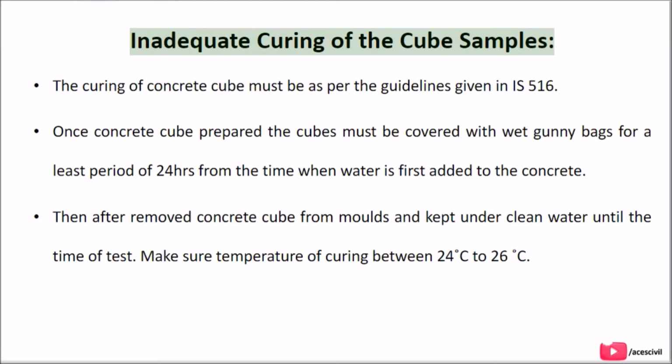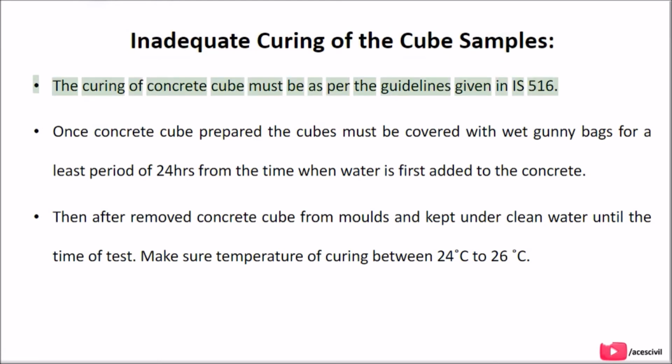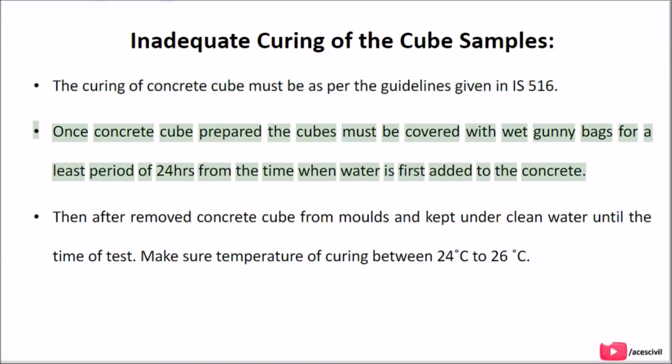Inadequate curing of the cube samples. The curing of concrete cubes must be as per the guidelines given in IS 516. Once the concrete cube is prepared, the cubes must be covered with wet gunny bags for a period of at least 24 hours from the time when water is first added to the concrete.